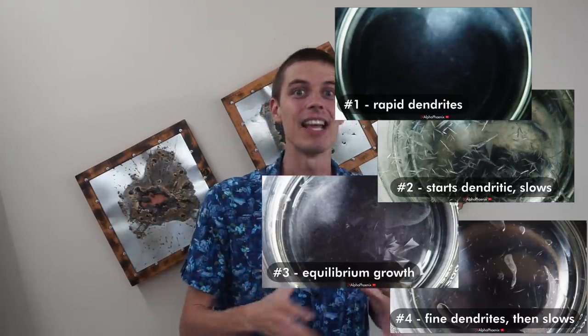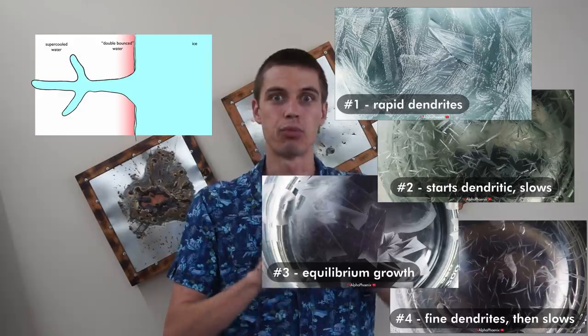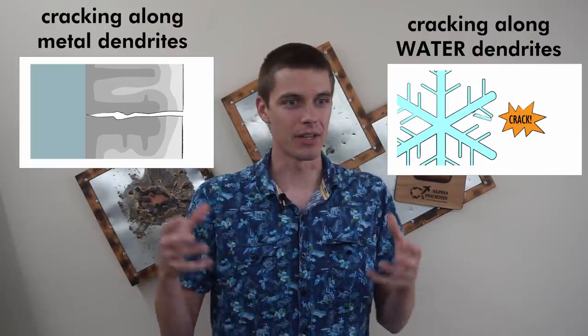All of that said, I want to clarify that this is at best a hypothesis. In science, we always have to temper our results. With the four videos of this process that I have recorded, I can say that the crackling noises occur during dendritic growth — during this kinetics-driven, very rapid branching growth of water ice. But as soon as that process slows down and presumably the water has warmed up to the point where you no longer have the inverse temperature gradient and can't grow dendrites anymore, when we just have ice growing normally there isn't any noise. Based on some level of intuition, reasoning about what could cause this, as well as looking at literature on dendritic growth and cracking in other material systems, I think that the mechanism I've proposed for why rapidly growing ice makes loud cracking noises is pretty reasonable.